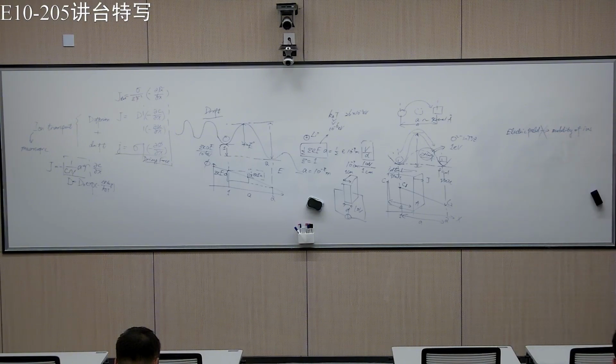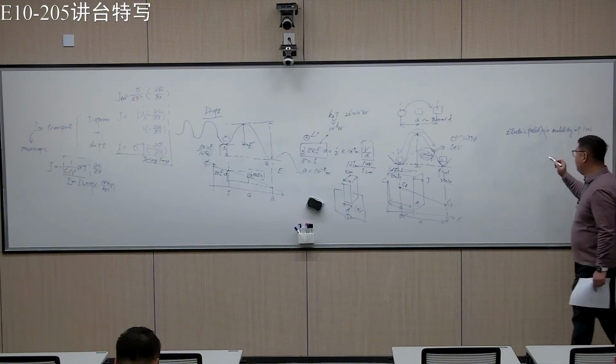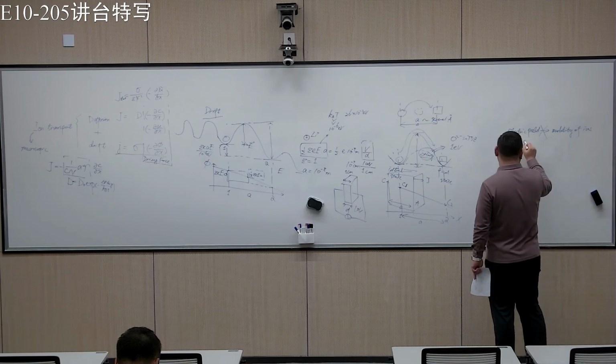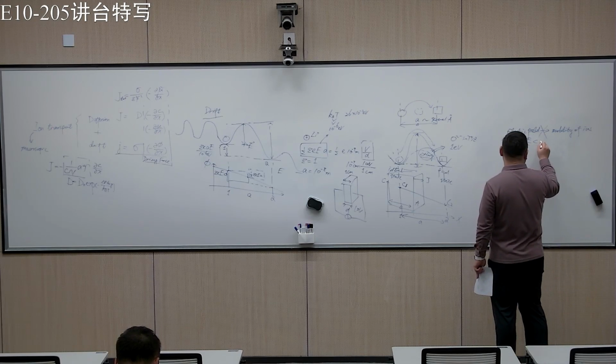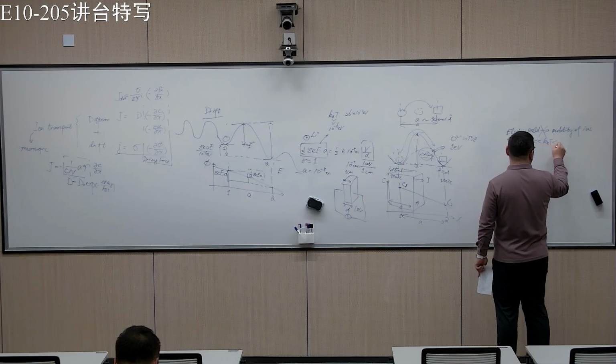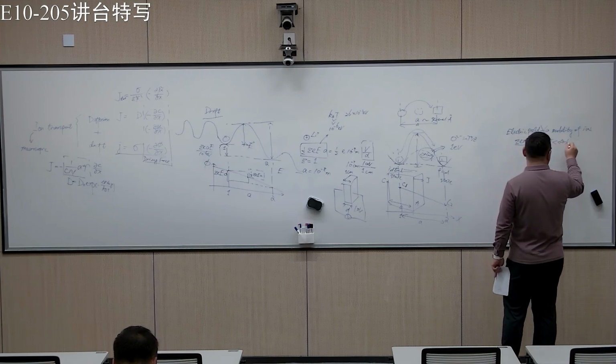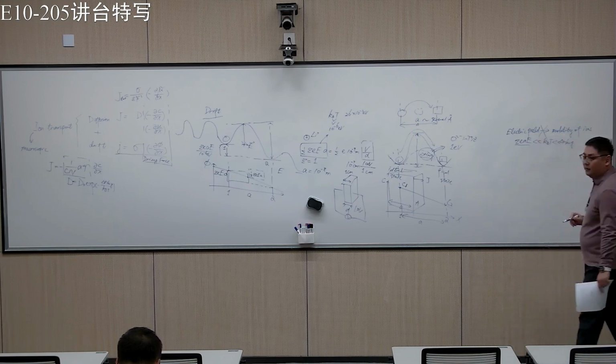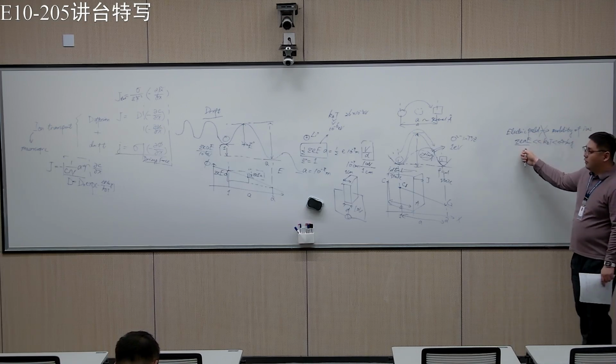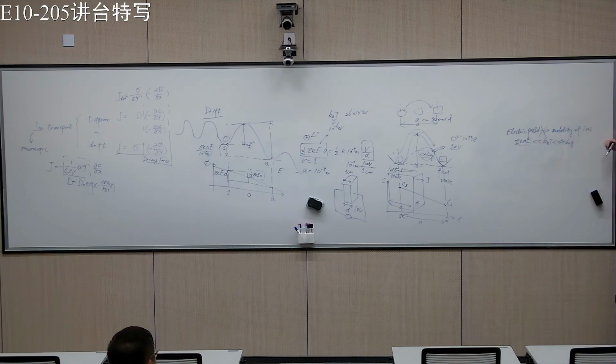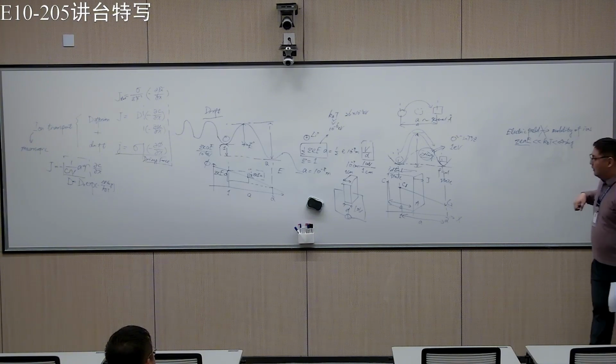Simply because in most cases this term is much smaller than kBT, much smaller than the direction migration. So this quantity cannot really have any meaningful change to the barrier. We're going to see later.